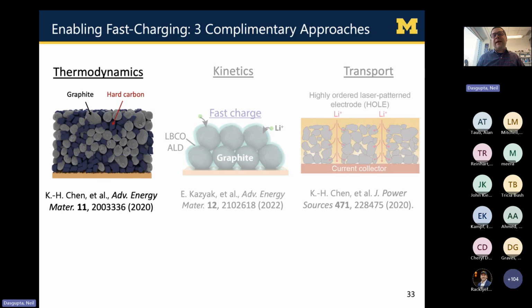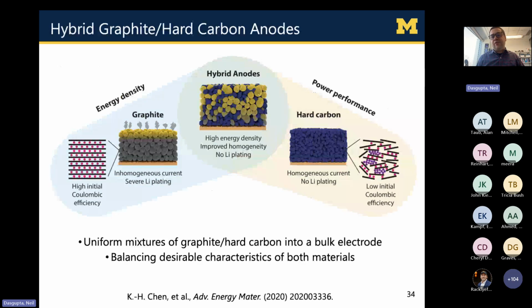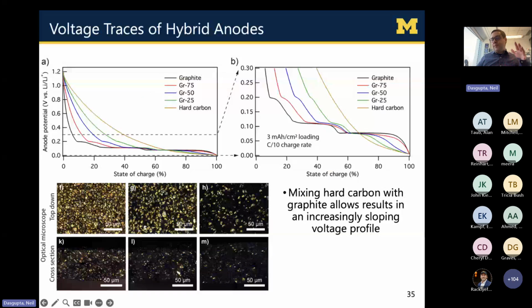It was discarded back a long time ago as a lithium-ion anode material because while it can actually enable faster charging, it has this sort of Achilles heel of having a low first cycle Coulombic efficiency. What that means is that you make the battery with hard carbon, the very first time the battery manufacturer charges and discharges it, it's lost 25% of the capacity of the battery. That's obviously not a desirable thing. Graphite is the one we eventually settled on that has a much higher initial Coulombic efficiency, but suffers from lower charging rate. So we asked the question, what happens as we start to blend these different types of carbonaceous materials together?